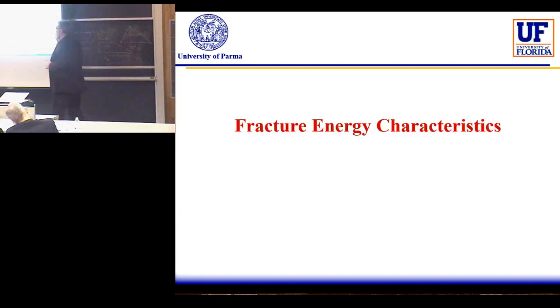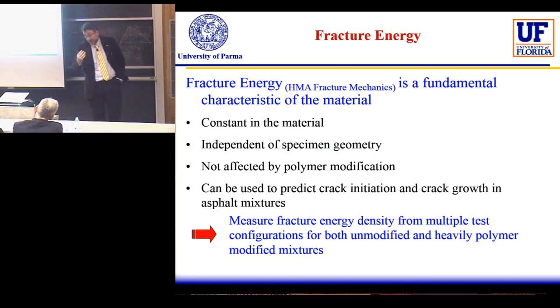Now let me go to the part where I was most involved, the definition of the different characteristics of the fracture energy. What I call a characteristic of the fracture energy is that we were able to verify that the fracture energy defined following the HMA fracture mechanics is constant in the material. So we were able to calculate, thanks to the DIC approach, the fracture energy at the different points where the crack started, and we had the same level of fracture energy at the different points of the material.